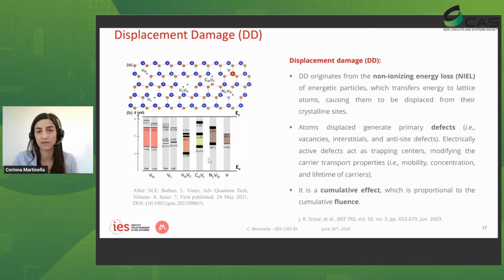So they can modify the carrier transport properties of the material, such as the mobility, the concentration, and the lifetime of carriers. Again, it's a cumulative effect, and generally when we talk about displacement damage, we refer to the fluence, so the number of particles per square centimeter.